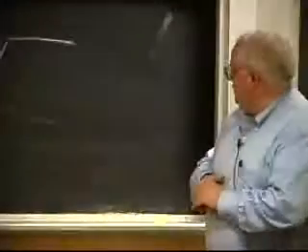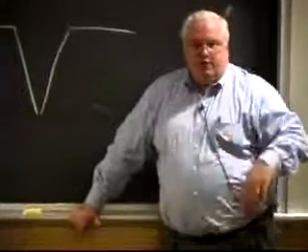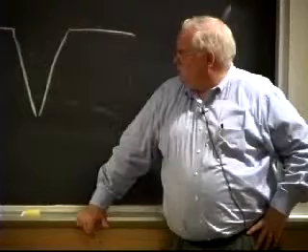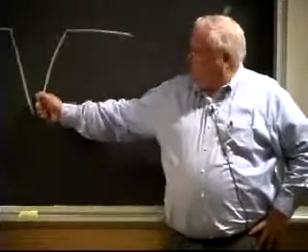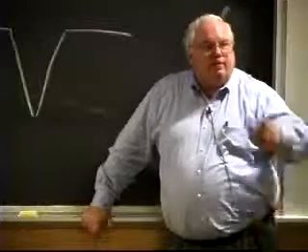Teflon's got one of the lowest surface energies, about 20 ergs per square centimeter. You know, metals are 1,000 ergs per square centimeter. Ceramics are 400. Most polymers are 70 or 80. But Teflon, because of this fluorine-carbon bond, which is fairly stable, has the lowest surface energies of any material, well, not Teflon itself, but the fluorinated hydrocarbons. If you go to Zisman, he shows different fluorinated hydrocarbons, and some of them get down as low as 17 ergs per square centimeter. How can I get, anybody have an idea, how to get the water down in here on the Teflon?